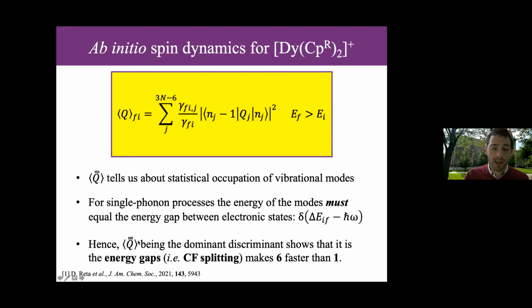Okay, and so it seems like a trivial result after all that effort that it's the crystal field splitting: make a bigger, more anisotropic single molecule magnet and you make it better. But that is the result of this analysis. And by doing the exact same analysis, comparing the original Nature paper dysprosium molecule to Layfield's Science paper, we see more or less the same thing. There's a little bit of an influence of the spin phonon coupling playing a role. It's not as clear cut as this one, but again, it's dominated by the crystal field splitting.